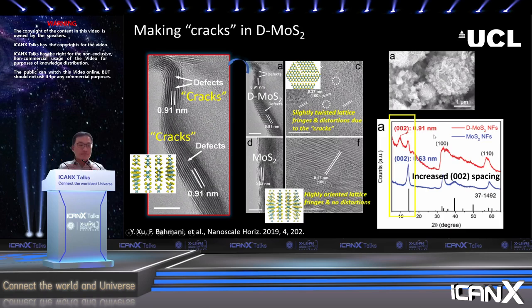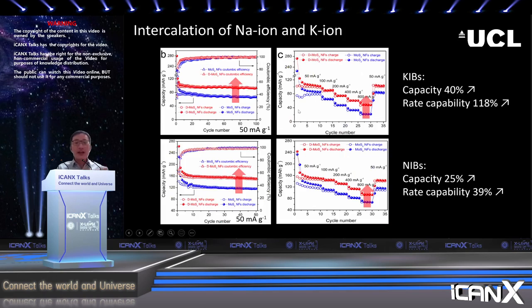We use this material in both sodium and potassium ion batteries, and we observed the enhancement of performance in both cases. In the case of potassium ion batteries, we observed a 40% increase of the capacity, and we also observed over 100% increase of the rate capability. And the increase for sodium is not as significant as potassium, but it's also encouraging. We saw a 25% increase of the capacity in the case of sodium, and also 39% increase of the rate performance in the case of sodium.